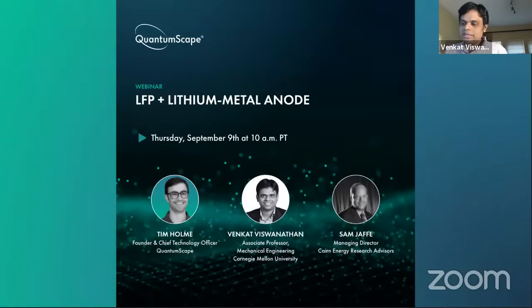One thing that is interesting in terms of the cost aspect of those two configurations is that using lithium foil typically comes with a conventional polypropylene separator and a liquid electrolyte. The lithium foil there is needed because the electrolyte is being consumed quite a bit more than when you have a protected lithium anode like what is shown here. So the lithium foil is another ingredient that adds to the active material cost, unlike the anode-free configuration where you don't have any of the anode cost. And of course, as a result, the associated plant area goes down.